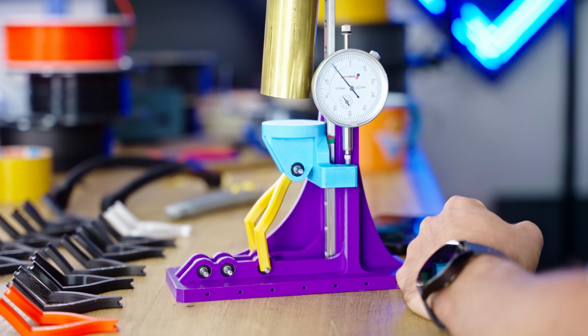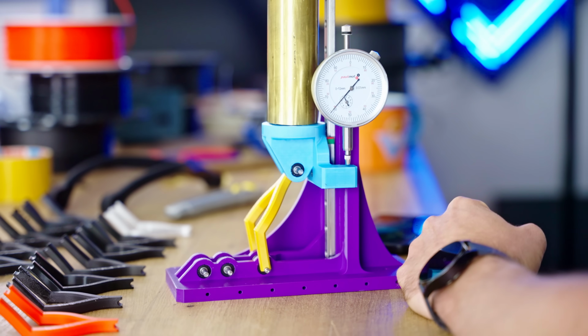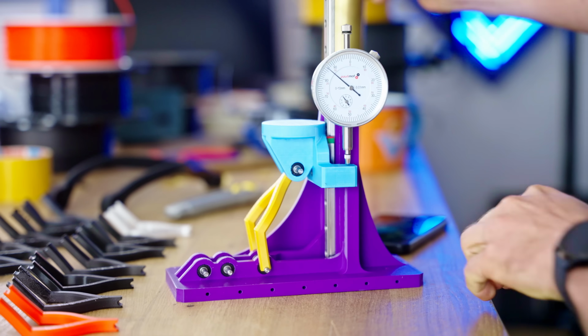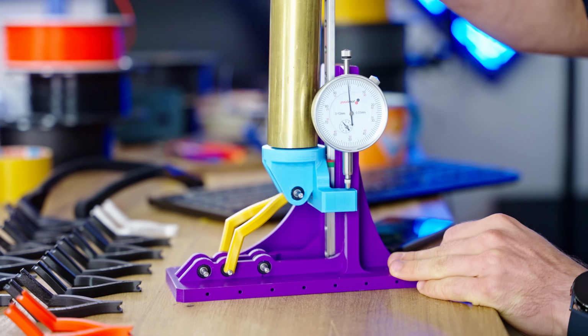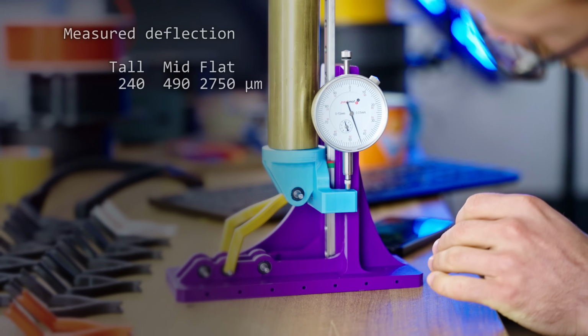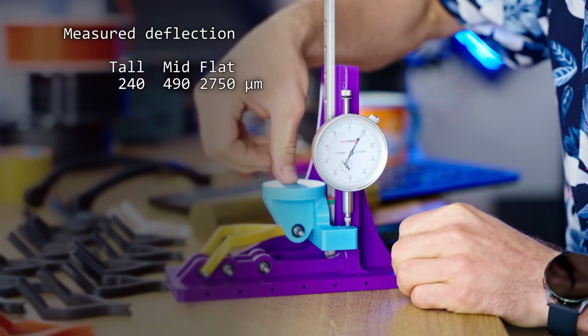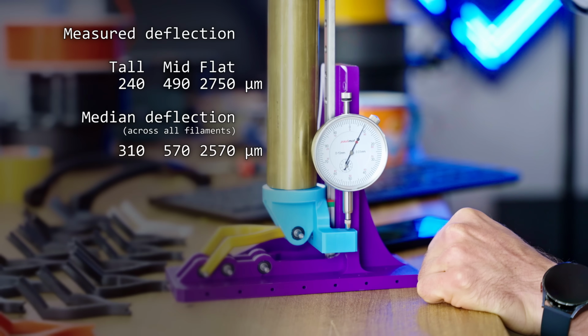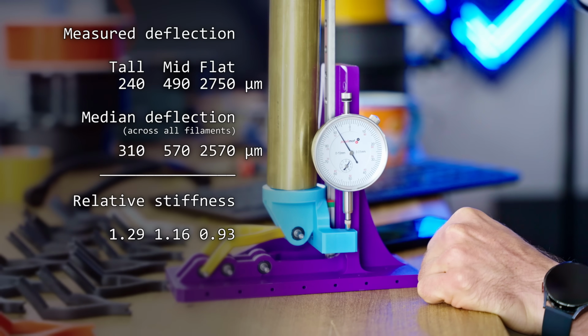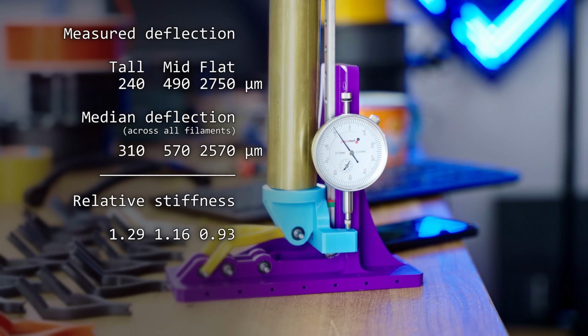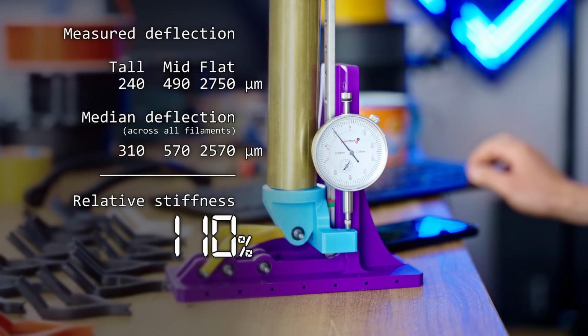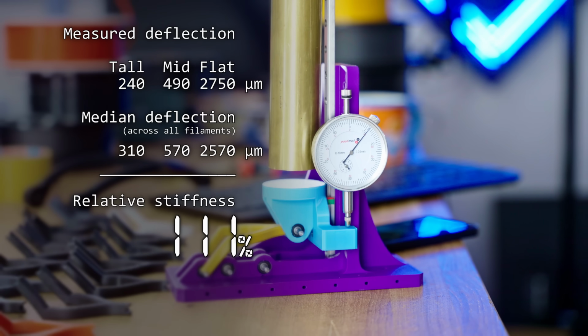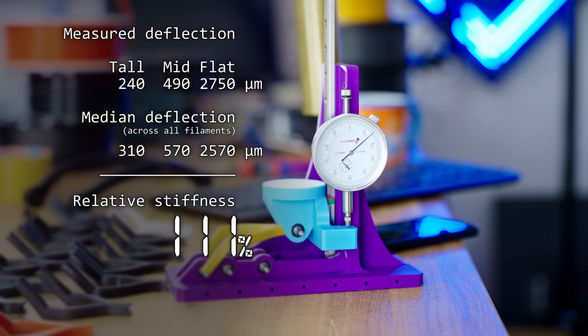The way that I'm measuring these is that I'm first loading the part with the weight and then measuring how far it springs back. And that just makes sure that both ends of our sample are seated on the pins properly. This is how much the voxel PLA deflected in each orientation. I can compare that to the median of how all the other filaments performed, and then average it across the 3 orientations. In this case, the voxel PLA got a combined score of 111%, meaning that in this test setup, the sample should be able to take an 11% higher load than the median average of the rest of the samples for the same amount of deformation. Or simply put, the sample is 11% more rigid.